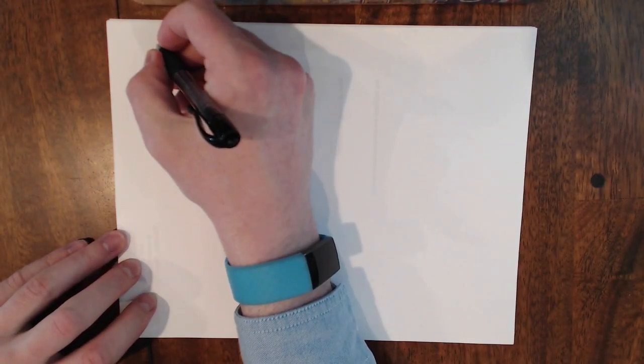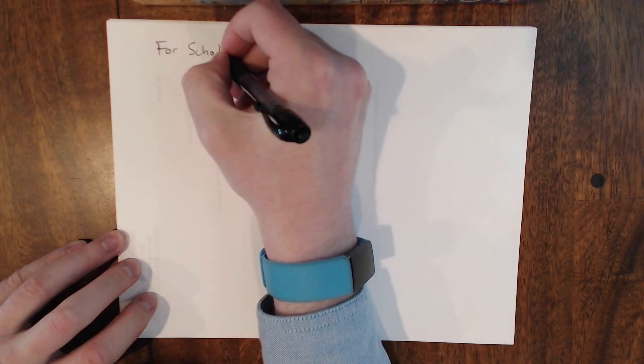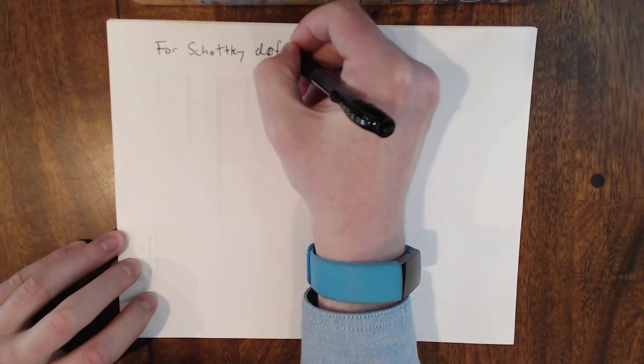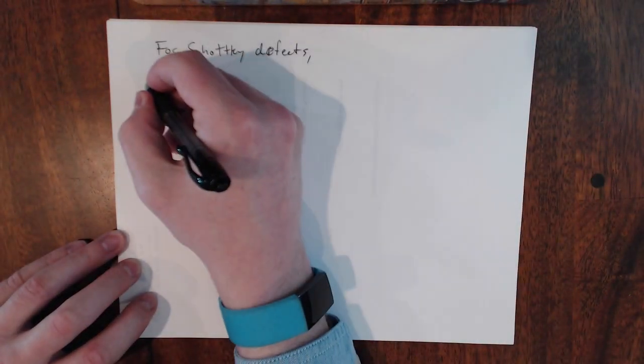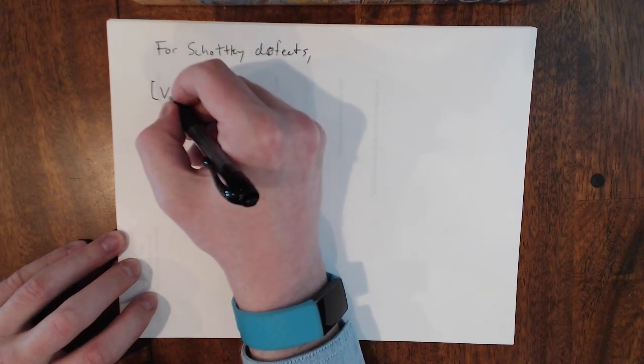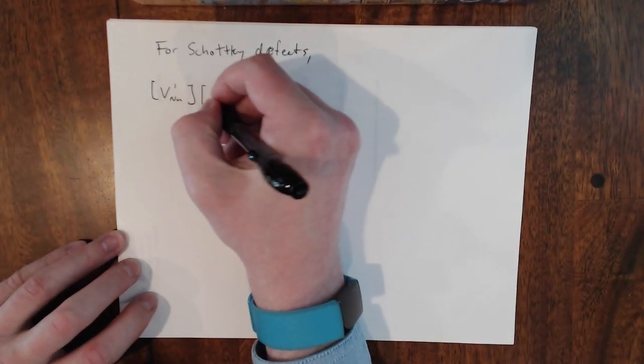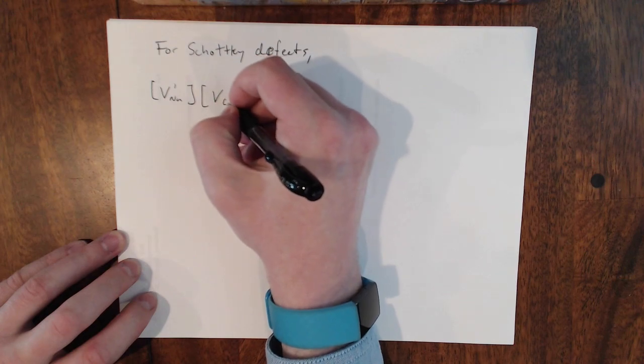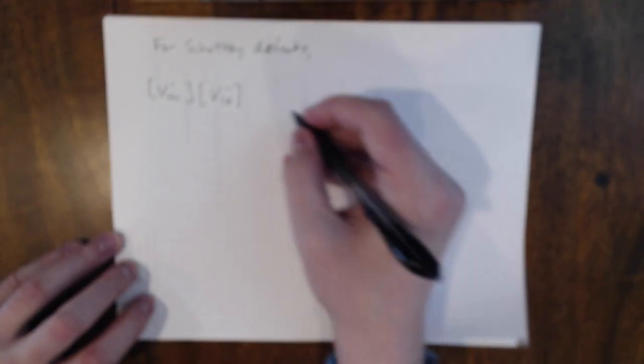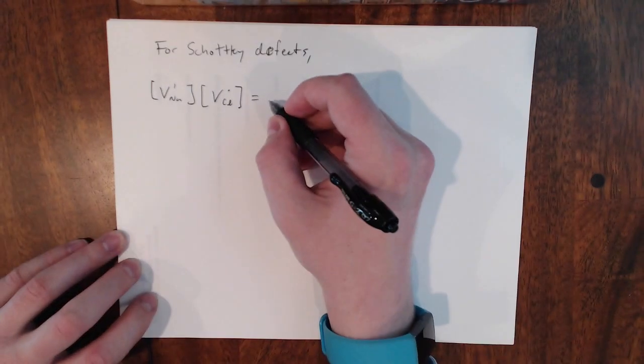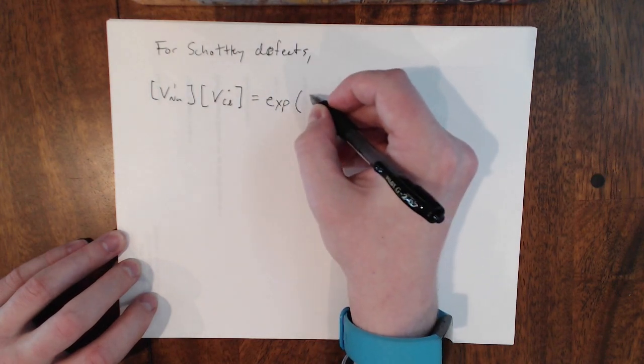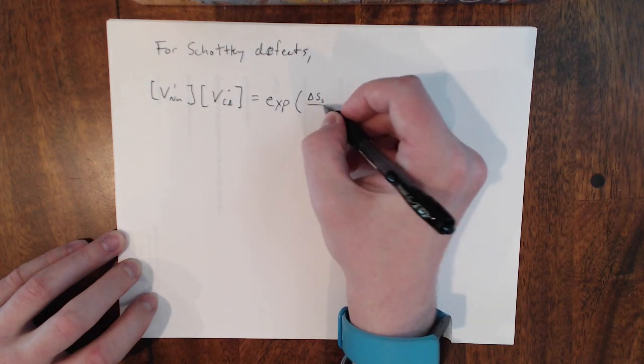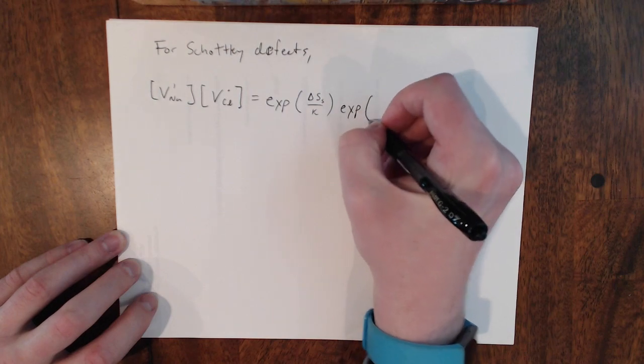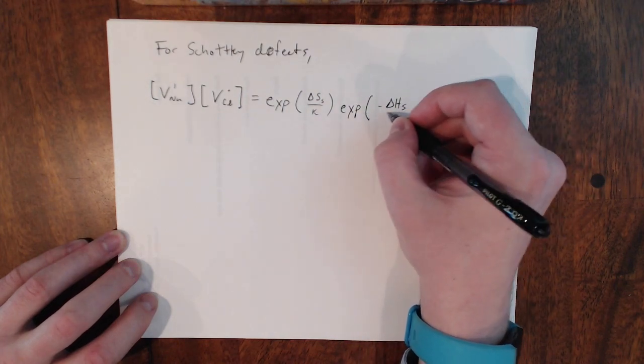So for, and I'm going to switch pages here. So for Schottky defects, our concentration of sodium vacancies and our site fraction of chlorine vacancies, right? So this is a part of a Schottky, and so see our previous lectures if that isn't clear. Is it going to be equal to an exponential of the entropy of Schottky's over K, and then multiplied by another exponential of the enthalpy of Schottky defects over KT.